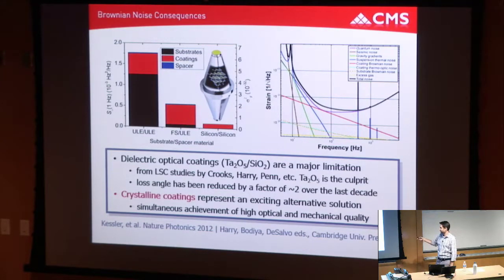But that coating noise line is a hard stop. Until you can increase the mechanical quality factor of the coating, you're not going to push the sensitivity below that floor. And this is something that LIGO has been approaching and will soon sit on once the Advanced LIGO interferometer gets up to full operating power.